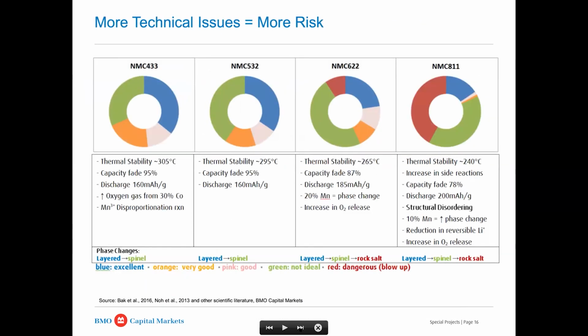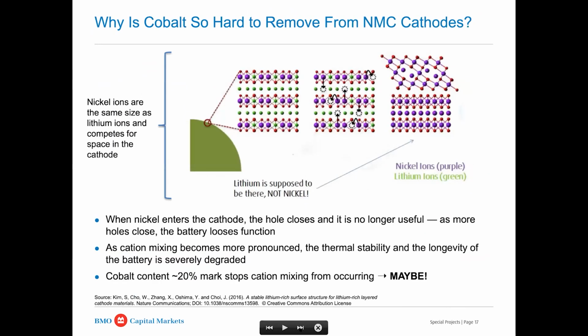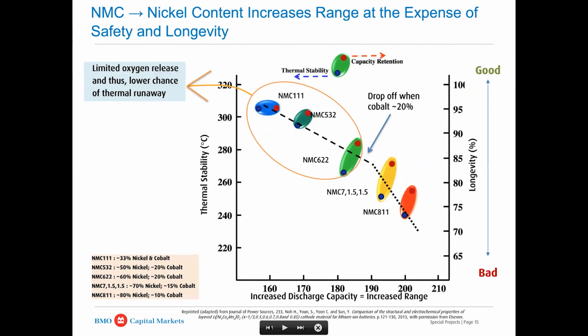So you look at this chart and it's like, okay, there's so many things going on as you increase nickel. Manganese, cobalt, all of these things, again, are trying to keep nickel out of trouble. And the main problem is that nickel competes with lithium within the system. These cathodes are intercalating, so lithium goes in and out as you charge and discharge, and that's how the battery functions. But the bottom line is that nickel will actually go into the holes where lithium's supposed to be, and it closes the holes. And so then you've got the structural decay, and they call it cation mixing. They basically just call it the mixing problem. And so it becomes more pronounced. And then obviously you go back to that original chart and you see that's why it goes down.